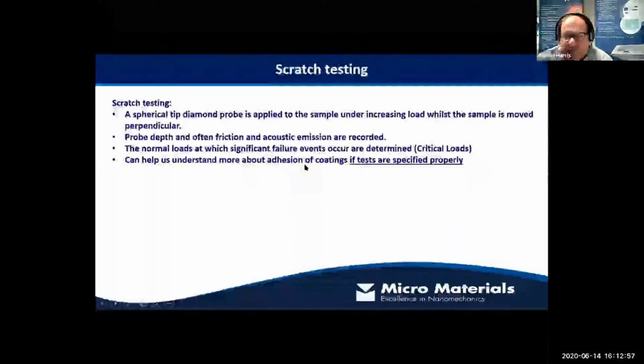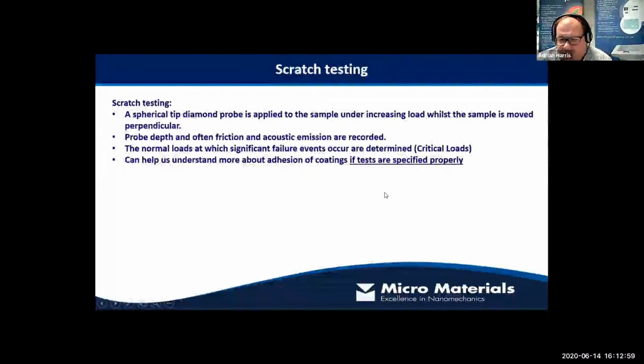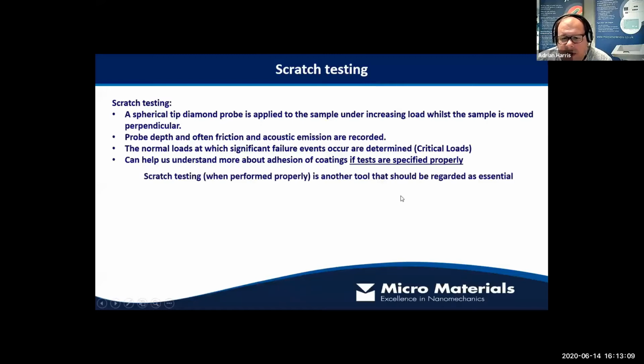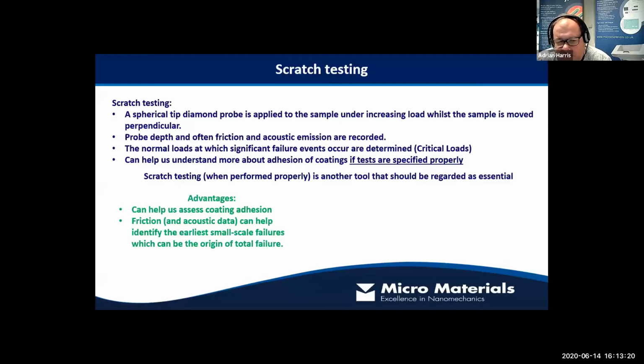Adhesion of the coating to a substrate is obviously key to its performance, and it's not something that we can easily predict, or in fact predict at all, through indentation. So this is a very useful complementary technique for indentation. So scratch testing, when performed properly, is another tool that should be regarded as essential. But again, it's got strengths and weaknesses.